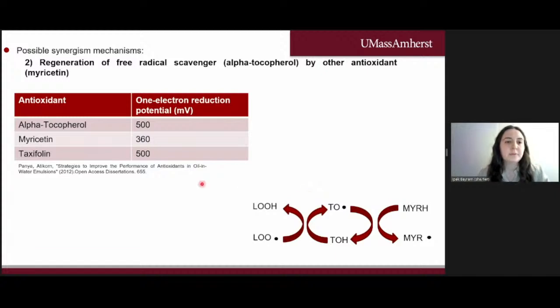The second possible mechanism could be the regeneration of an antioxidant by another one. We see that myricetin has a lower redox potential than tocopherol. Therefore, myricetin can actually reduce oxidized tocopherol back to its original state and improve its activity. This could be the reason why they acted synergistically. But tocopherol and taxifolin have the same redox potential, so they cannot regenerate each other.